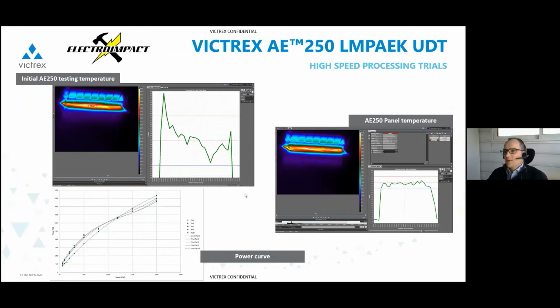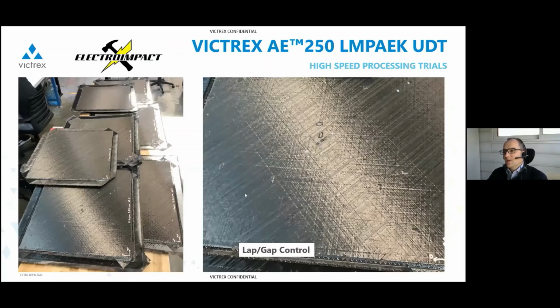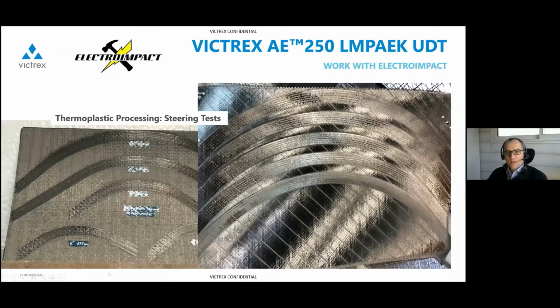So for high speed layup, this requires further refinement to better control the feeding of the thermoplastic material on hardware intended for thermoset material, to accommodate the kitting effect, the lap gap control, the course spread control. These improvements created a smoother surface, resulting in better temperature control and increased part thickness uniformity, resulting in a higher quality laminate. That's what you can see here. Many panels were made to fine-tune all those parameters, like for instance here, just the lap and gap control to end up with a thin, smooth surface. Some steering tests were also performed, and they were pretty promising. So it seems like the processing of the tape, even at a high speed, was quite promising.